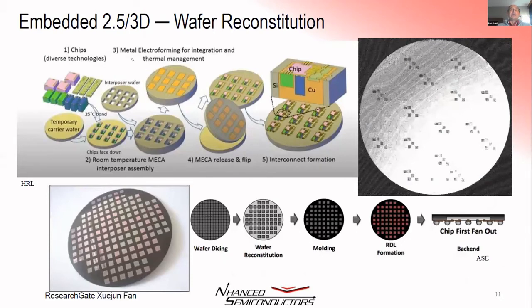Another interesting technology is what I'll call embedded 2.5 or 3D, really based on wafer reconstitution. Hughes Research Labs has a technology that embeds chips in a copper block that has some interesting niche applications, especially in the area of RF. As you can see here, the chips are basically placed face down on a carrier wafer. There's an interposer that's bonded to it with pre-cut holes that is filled with copper, and then you remove it off the original temporary carrier. You end up with this structure of chips of various technologies that are coplanar because they were put face down on the original wafer and then backfilled with copper. So the copper acts as a ground plane as well as a very large heat sink.